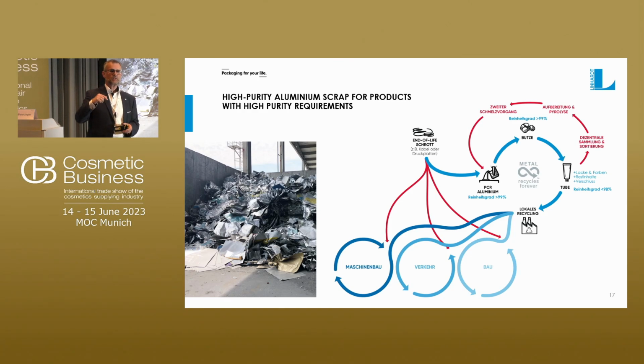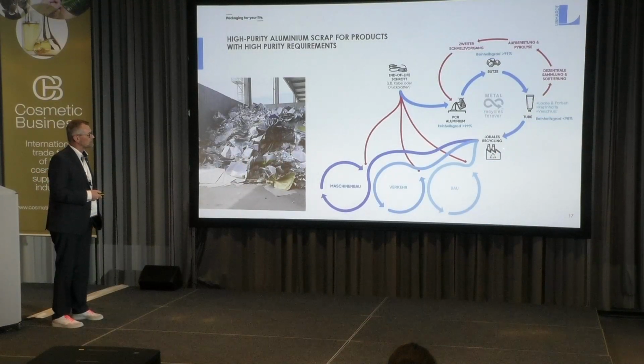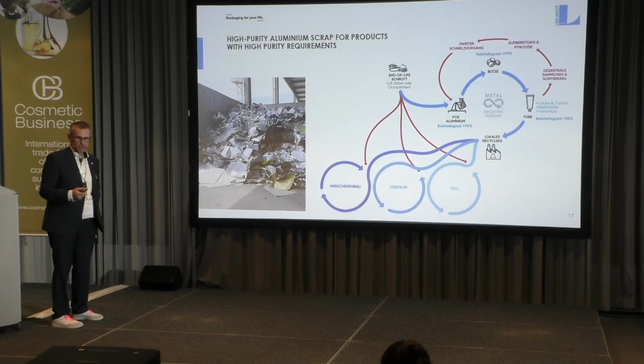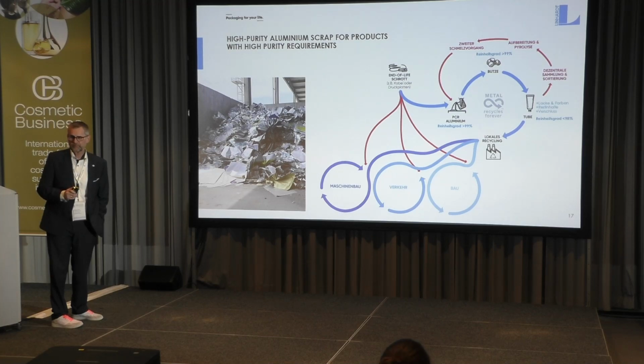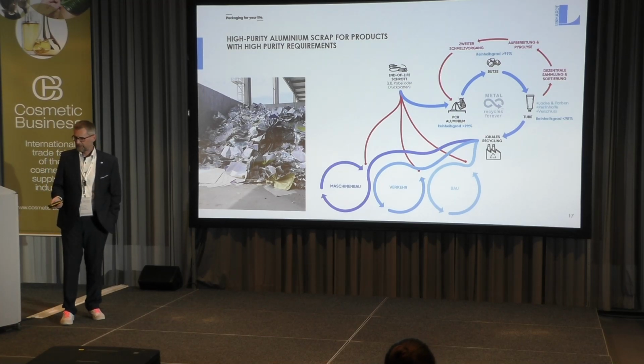So this is a very useful aspect. We use high-quality scrap and reuse it, and we can seize the high purity of the material. What you can see here on the diagram is we use end-of-life scrap, for example, cable wire or lithographic plates. It's not directly fed into mechanical engineering, the transportation sector, or the construction sector. We do another loop. It's molten, it's turned into tubes, and it's then locally recycled. And as a second step, it will then be fed into the recycling cycles of mechanical engineering, transportation, and construction. So the aluminum we use is not lost for these other sectors. No, we add another loop in order to seize this high degree of purity that the material offers. And this is the key fact here.